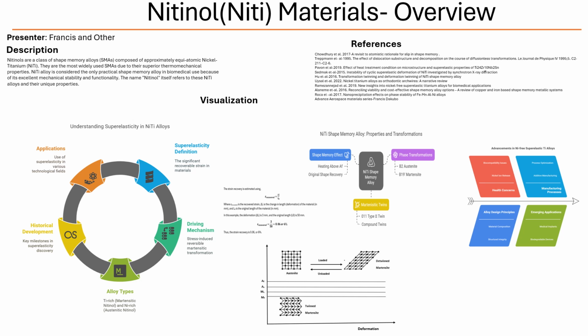Exactly. But those theoretical models don't always fully capture what happens at really high stresses and temperatures, because at those extremes, you start to get a lot of dislocation slip that happens independently of the transformation itself. And if you look at the material under a really powerful microscope, like a transmission electron microscope, you can actually see all those slip dislocations, which clearly contribute to that permanent deformation. So it's almost like the transformation process itself can create the right conditions for that problematic slip to occur.